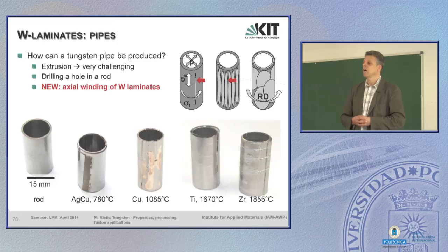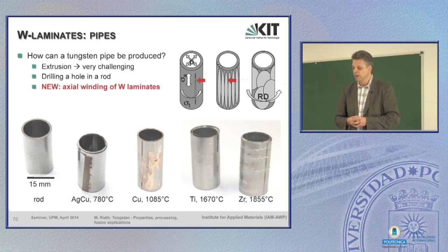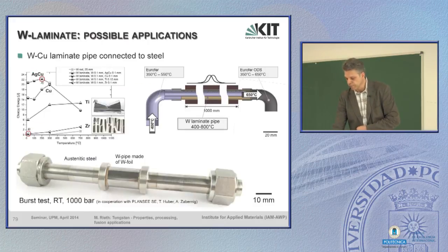And pipes can be simply produced, as we have seen, by rolling. We wrap up these foils and then join them together, and in the end we result in pipes. The advantage over a rod with a hole drilled inside, where we have this unfavorable grain distribution, is that here the platelets or pancakes in the foil are oriented circumferentially around the pipe, which makes the best possible load application for such a structure.